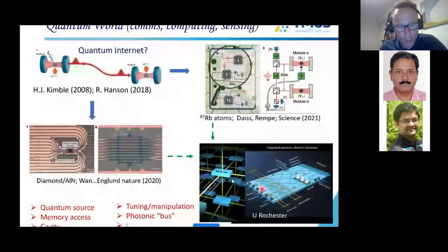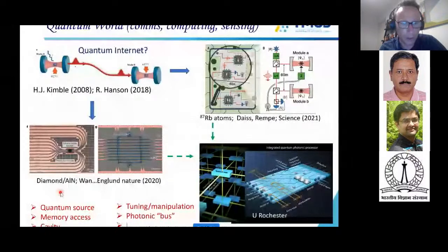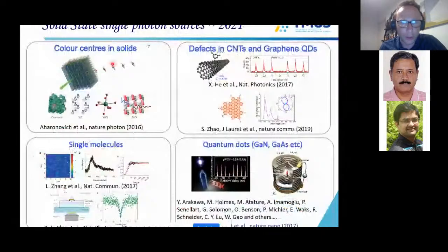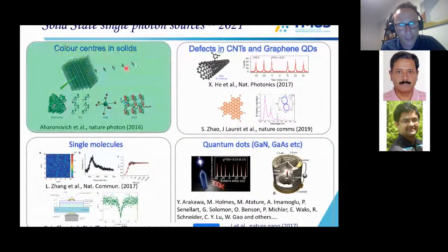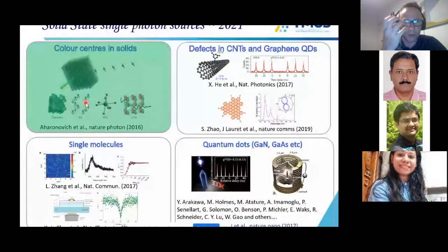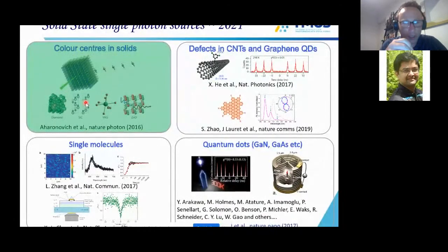So our effort is predominantly focused around the single photon sources or the quantum light sources. And if you look at the library of single photon sources, there are actually quite a few of them: defects in carbon nanotubes, and of course quantum dots and molecules and color centers in solids. We are very interested in this system in particular for many reasons, but one of them is a very practical one for students to work with. This is because it operates at room temperature, and you can have your diamond or your hexagonal boron nitride or silicon carbide in your hand, and if you drop it by accident on the floor, you can pick it up, and the quantum system is so robust operating at room temperature that you can put it back under your confocal microscope.